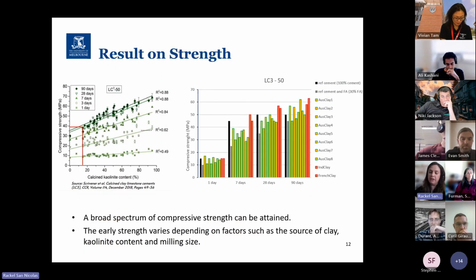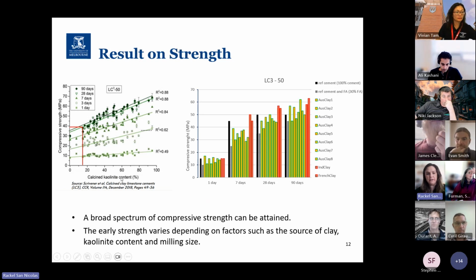So maybe just a really quick overview on what kind of performance those materials have. So here I just pulled out some from the literature. On the left-hand side, there is a wide range of compressive strengths in respect of the amount of calcined clay and the kaolinite content in your system. So the system is always the same. In this system it's an LC3 with 50% of cement substituted, not by calcined clay only, but by calcined clay and limestone.